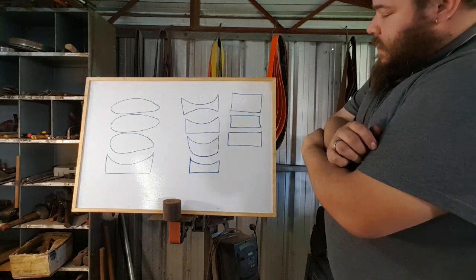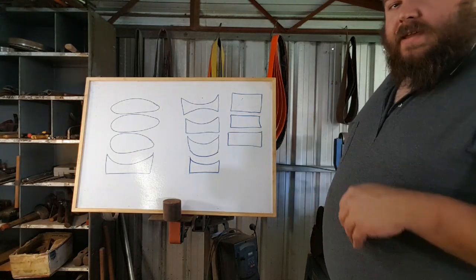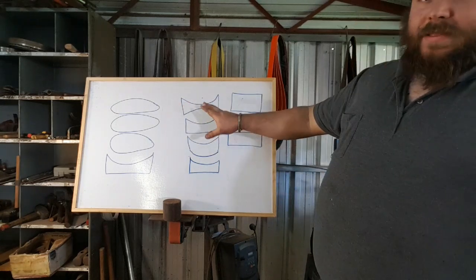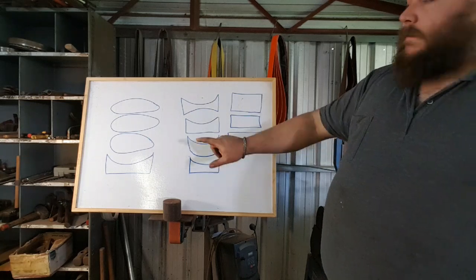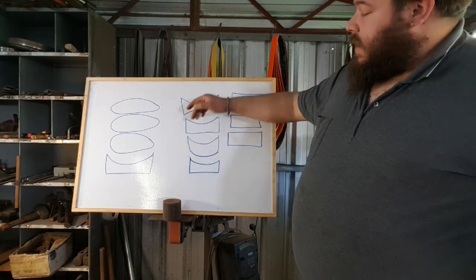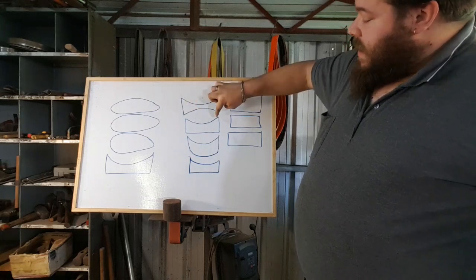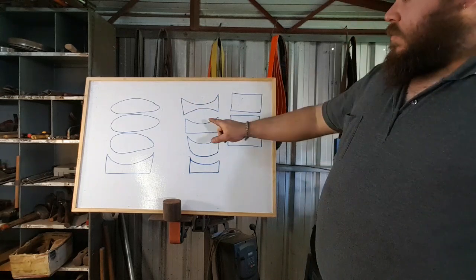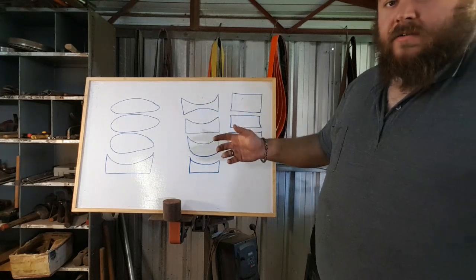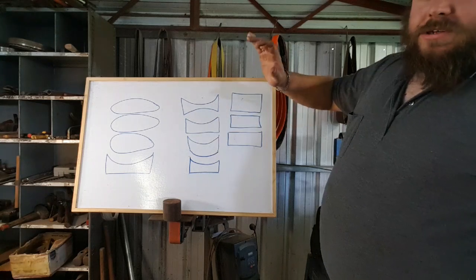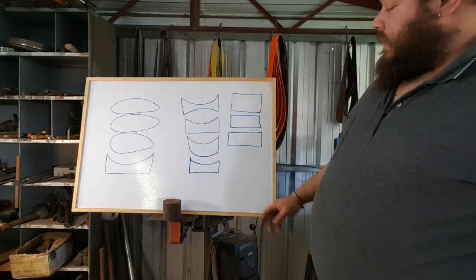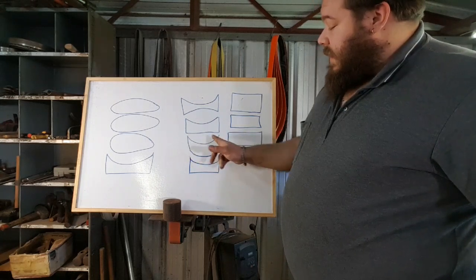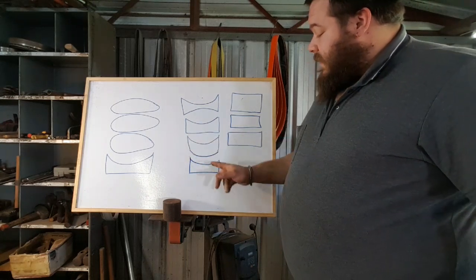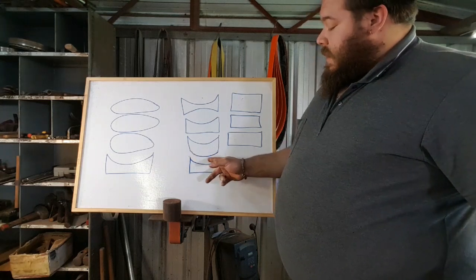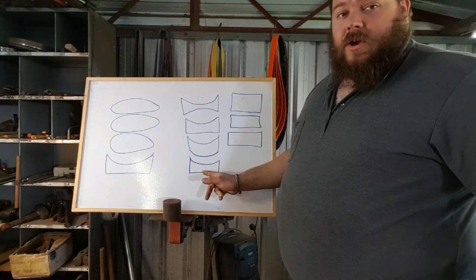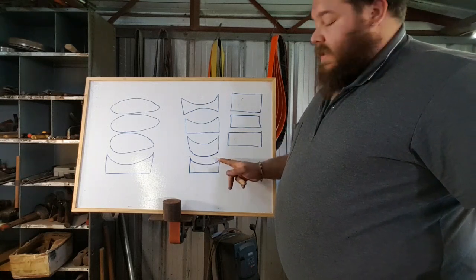But in the event that I was using an angle grinder and you happen to keep the disc in the center of the piece for too long, and it doesn't have to be this bad, it just has to have a slight dip, then you're creating a pocket, and even if you strike in the middle, these edges are going to weld first. That means you're going to end up with a pocket of borax or just iron oxide in the billet, which is going to mean that your forge weld is never going to work. Even when done with a flat piece, obviously you have the high points that are going to weld onto the flat piece, and even if you've got a concave piece, unless the concave is larger than the dip that you've got, you're not going to hit the center before you hit the edges.